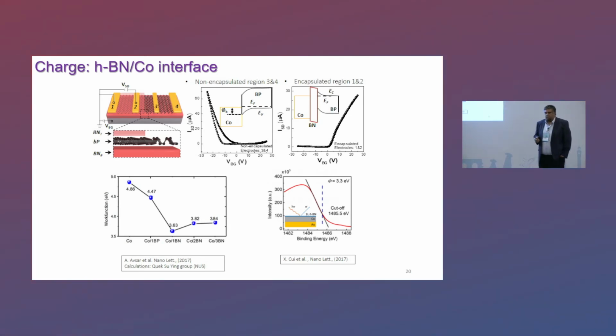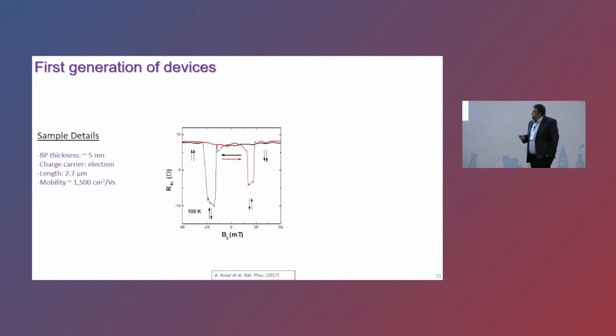It goes from 4.8 EV to around 3.8 EV. There were also very similar but different direct measurements of this effect by a group in Colombia, which also demonstrated that if you have a thin layer of boron nitride under cobalt, the work function is significantly reduced. So whenever you are reducing the effective work function in your device, your Fermi level comes closer to the valence band, therefore you have this p-type behavior. Okay, so this is the first spin transport measurement we did about 5 years ago.